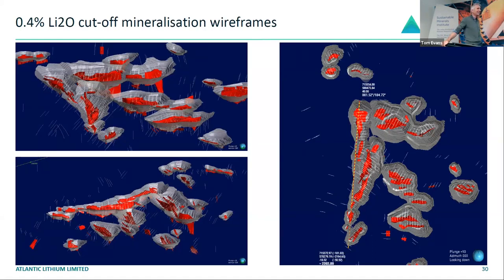No, I'm not. So I guess an observation and then just a couple of little questions. If we were 100% spodumene in our con, we'd still only be 8% lithium oxide, right? So hence the 70-80% con gives you the 6%. Correct, yeah. So the 6% con actually originates from Greenbushes. It's just what Greenbushes was able to produce through their process flow sheet and what they've been selling into the market, and it's become the accepted name. Like iron ore has the lump or the high phosphorus blend, for example. It's just a volume of material that's been accepted by the market, and it's now become the gold standard.